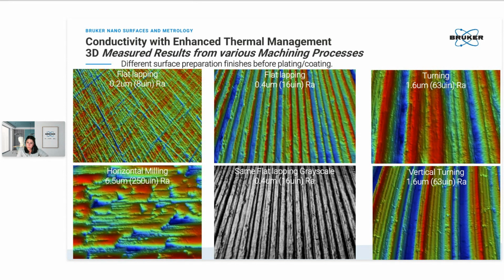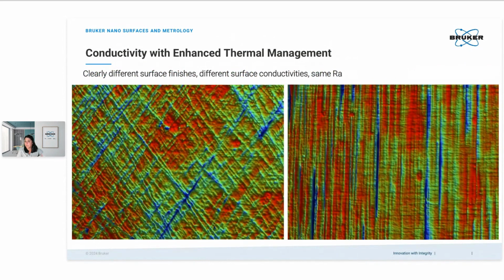But of course, the roughness itself, which is a very standard parameter, the Ra, which is the mean roughness, shows in some cases, like on the very right side, on the turning and the vertical turning, the same Ra value, but the surface itself looks different and would also need either a different coating or a different way of coating, or they would also have a total different conductivity. On the next slide, you can see it even more clearly. We have here totally different surface finishes, a total different way how this surface would lead the current or would distribute the current, but it has the same Ra value.